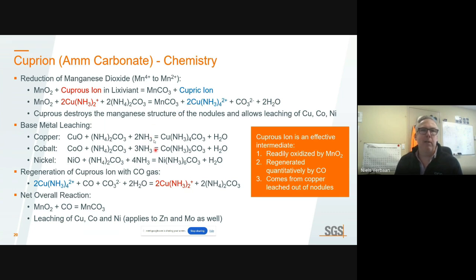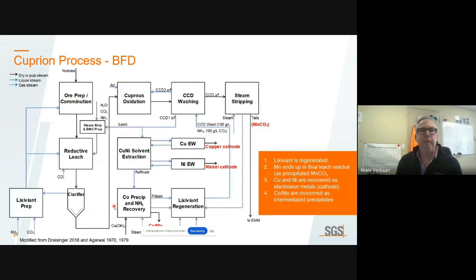So that's the second step here. And the third step is the regeneration of cuprous using carbon monoxide gas. So cupric with carbon monoxide forms the cuprous ion that can be reused, and the net overall reaction is shown here. Here's the flow sheet that is proposed. The leaching step is shown here. The leach liquor is oxidized, so cuprous goes back to cupric, and it goes through a solvent extraction step, electrowinning to make copper cathode, nickel cathode.